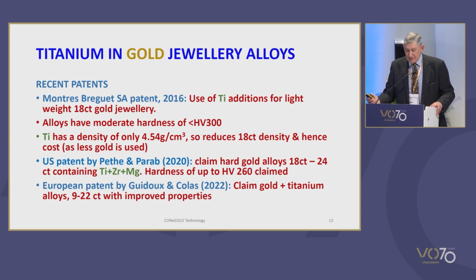The main aim here is to produce lightweight alloys for watch and jewellery applications. With a density of only 4.54 grams per cubic centimetre, its use in alloying with gold can make a significant impact on alloy density and hence cost of jewellery. In another patent, a US patent in 2020, the inventors Pethe and Parab claim hard gold alloys of 18 to 24 carat containing titanium, zirconium and magnesium in combination for jewellery manufacture, again with a beneficial impact on alloy density. Hardness values of up to 260 Vickers are claimed.